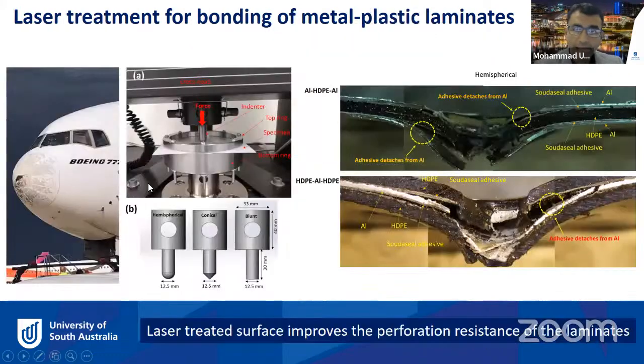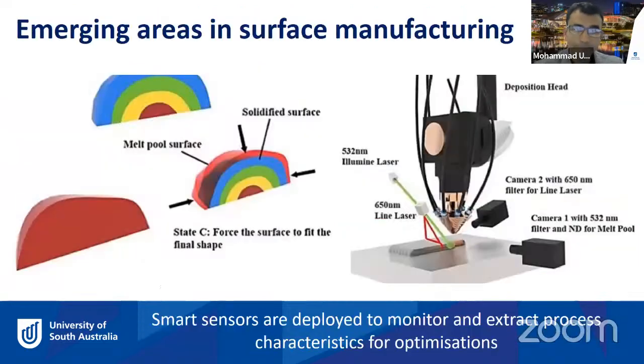And we have also done some tests after the laser treatment, where we make the bonding of the sheets and make the laminates. And then we also investigated the perforation resistance of the laminated sheet, or metal plastic laminates, with three different types of indenter: conical, hemispherical, or blunt. And we found that the failure of the laser treated laminates showed a very regular and good performance as well.